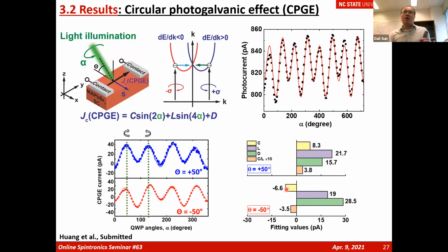But again, here we only demonstrate the oscillating photocurrent according to different circular polarization illumination. That can be caused by chirality. If somehow your single crystal forms a chiral structure, of course you have different absorption coefficients, and the photocurrent you measure will be circularly dependent. So again, it's not a perfect effect to address the existent Rashba effect unless we're able to demonstrate the spin-dependent feature upon the circular polarizations.